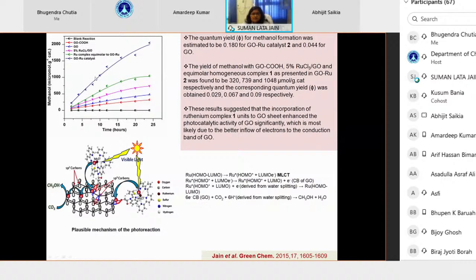this is our hybrid system, which provides a significantly higher yield of methanol in comparison to the various combinations. We can compare with the bare complex, with the physical mixture, with the functionalized support, or with the bare semiconducting graphene oxide support. Among all the combinations, our hybrid system provided the better efficiency, better yield of methanol from carbon dioxide, and higher stability. We can easily recover it after the reaction, and it could be reused for at least 4 or 5 runs that we checked in our laboratory.